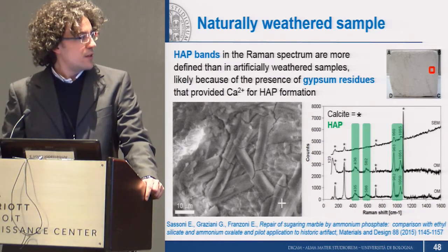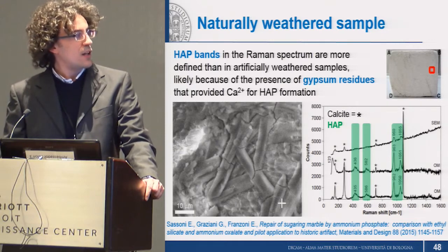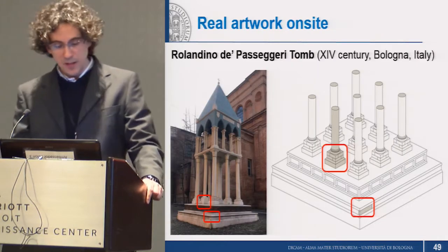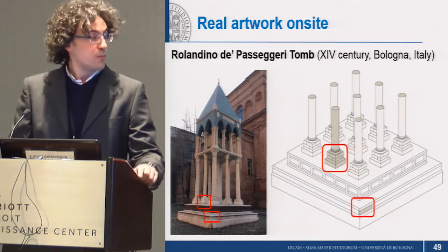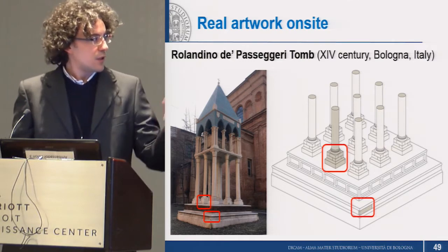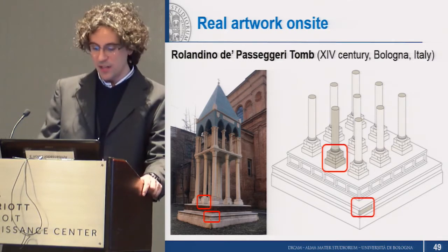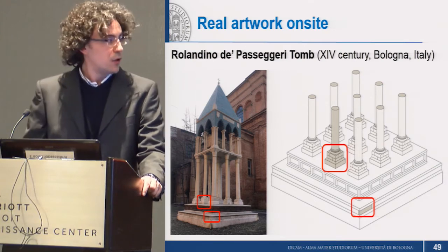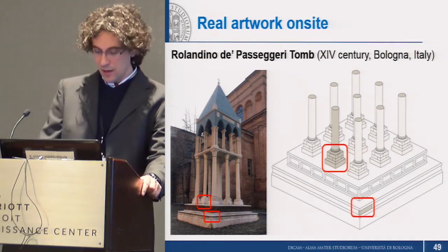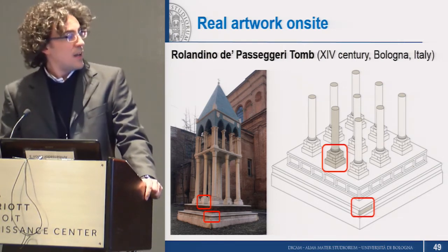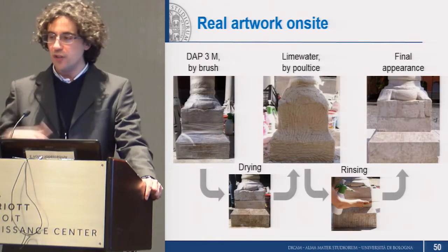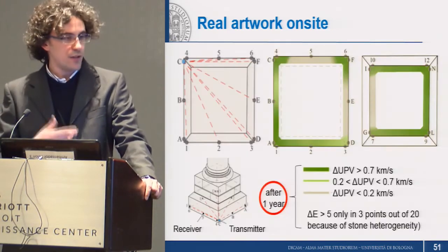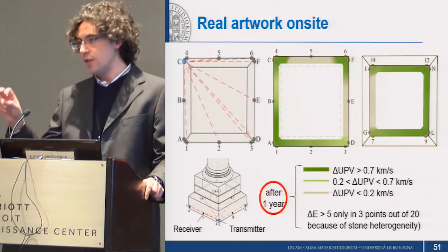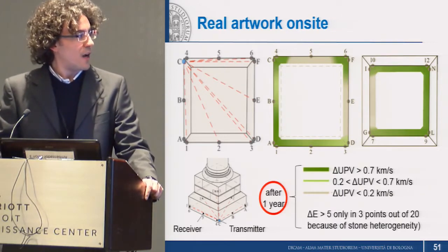Starting from this, we also carried out some preliminary applications in the field on a gravestone, a tombstone in Bologna. So we treated one base and one element in the basement of this tomb, carrying out the same procedures that I explained, and then checked immediately after the treatment and after 1 year, just to check the durability, the relatively long-term effects of our treatment.